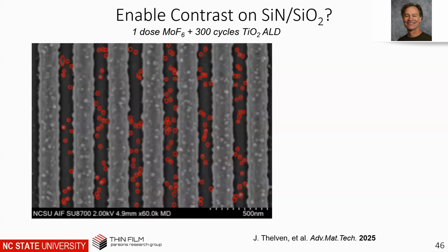And I said, I want you to go in and figure out what fraction of this surface is covered by those dots, by the defects, those little tiny dots. It turns out where we want the film, it's 100% covered, obviously. It's covered everywhere. Where we don't want the film, it's 3.8% of the surface.